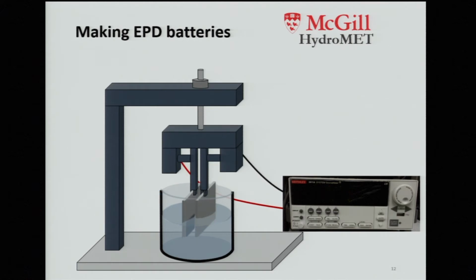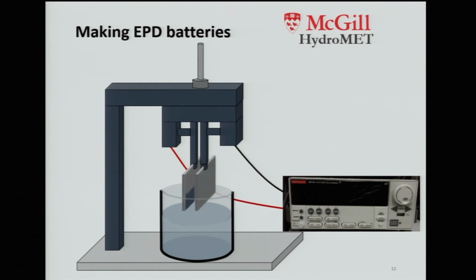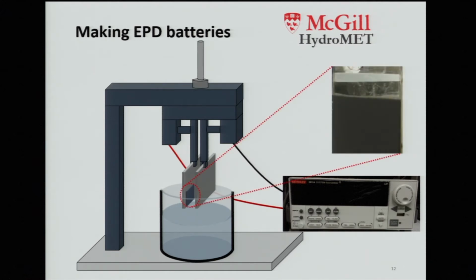We can then remove the coating and allow it to dry and repeat this for as many times as necessary to create a thick enough coating. And this is what our coatings end up looking like. The back or gray part there is the aluminum foil that we submerged, and on top of it is the EPD coating that we just made.